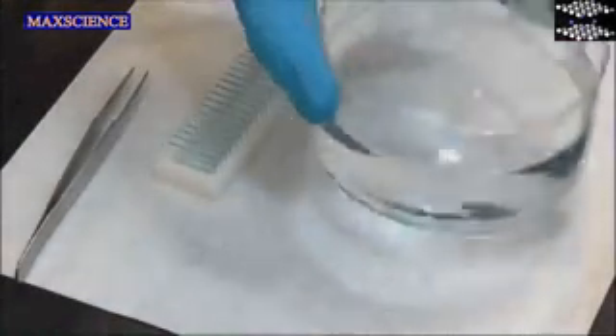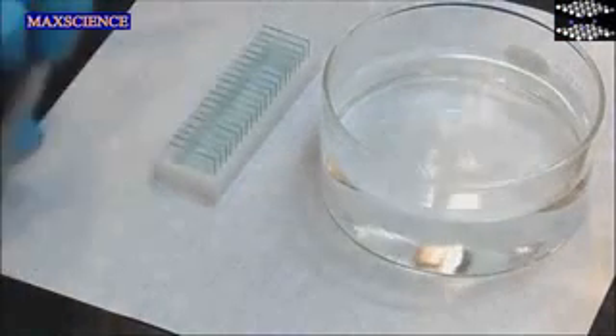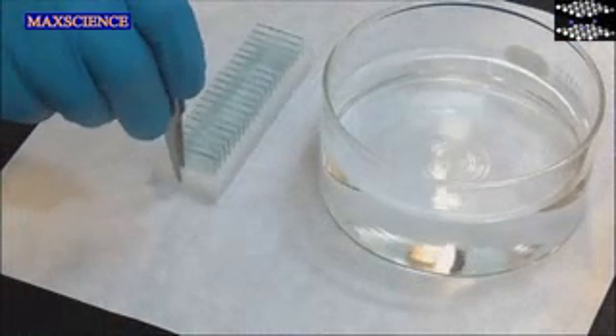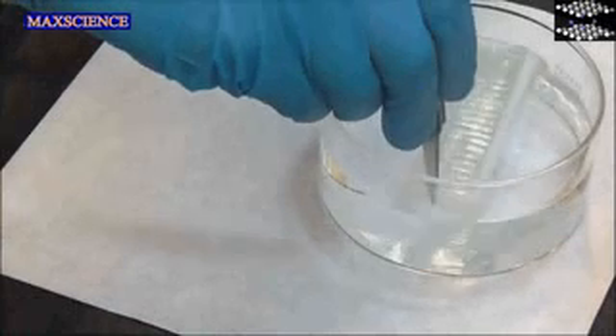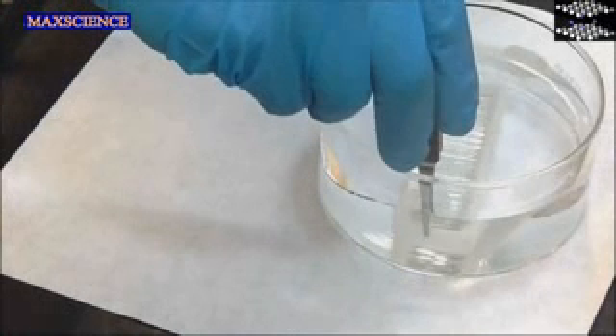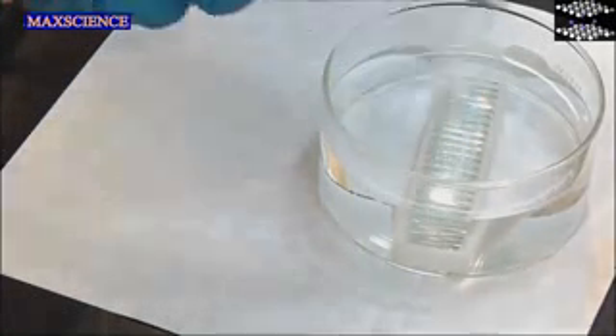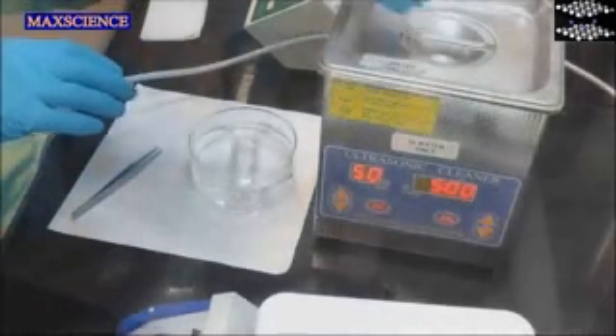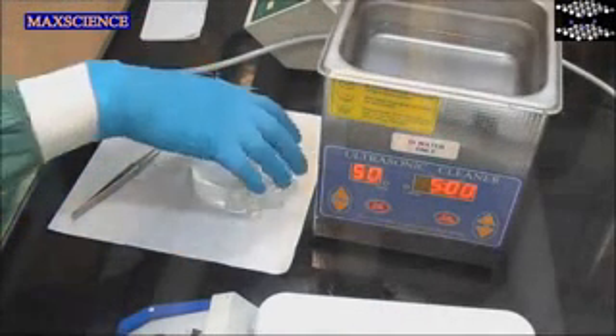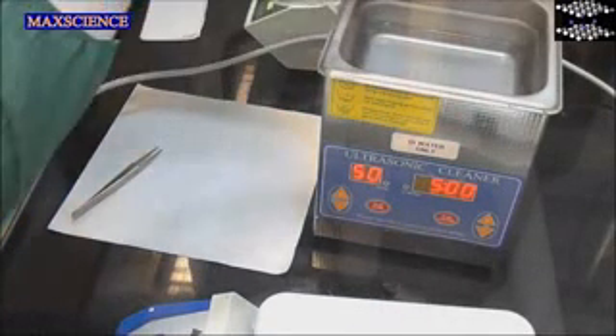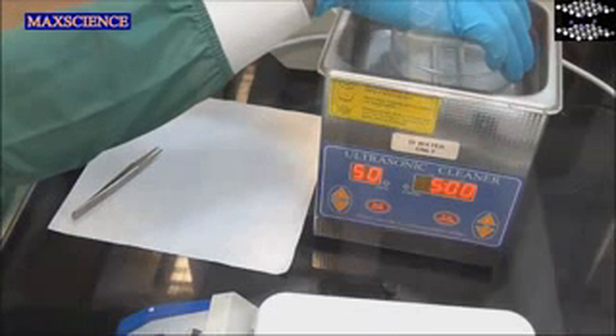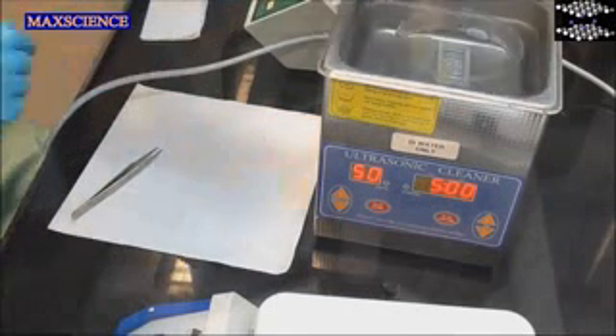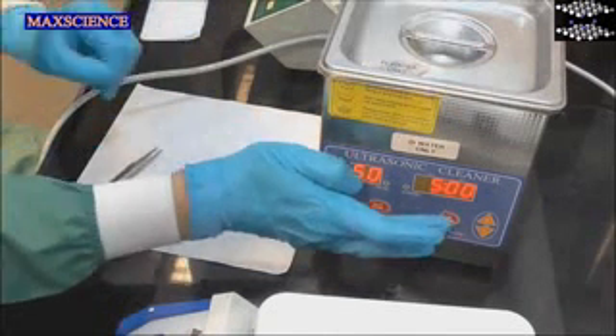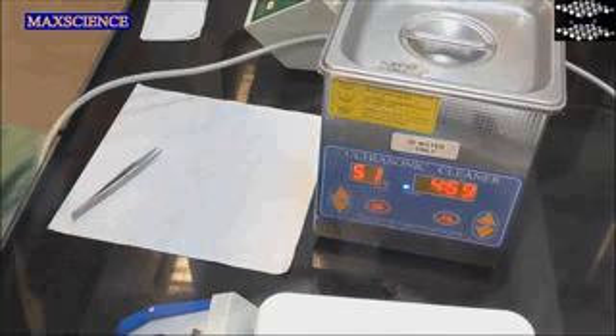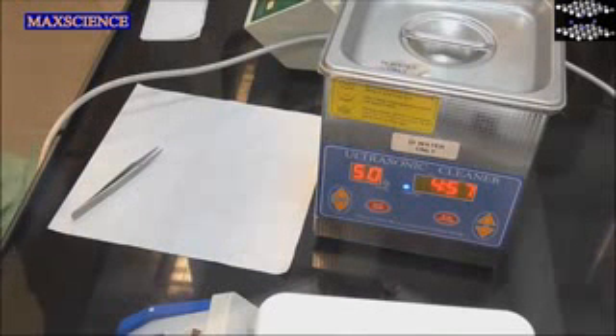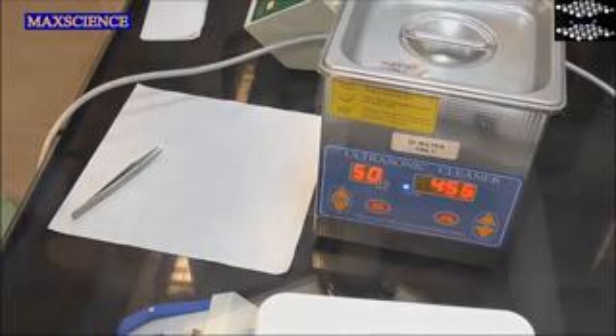Prepare a clean glass beaker with boiling deionized water containing a little Hellmanex solution. Then place the beaker into an ultrasonic bath, fill with boiling deionized water and sonicate for 5 minutes. The ultrasonic bath causes rapid vibration to occur around the substrates, aiding the removal of particulates.